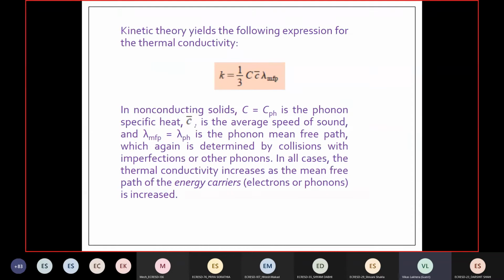If you see the kinetic theory, it suggests that the thermal conductivity expression is given by this, where lambda is the mean free path. If you can manage this lambda, the mean free path of the phonon, then you can lower the thermal conductivity. This is what is used in nanotechnology, and this is what you are doing when you are creating the aerogel or the microporous insulation. Once you reduce this, your conductivity also reduces. If you want to increase k, then you should increase this lambda. So the mean free path of the energy carrier is how you can control the thermal conductivity, and this is what aerogels do. Otherwise, the lowermost limit is constrained by the mean free path of the air molecules.